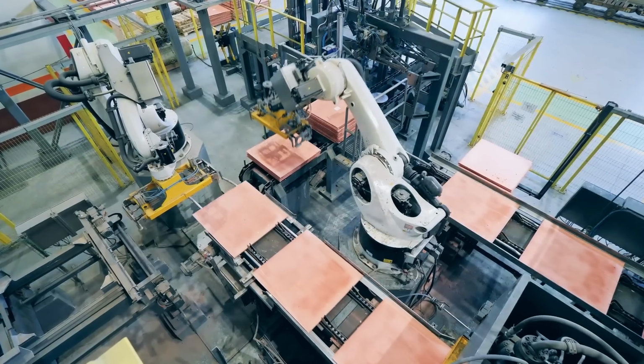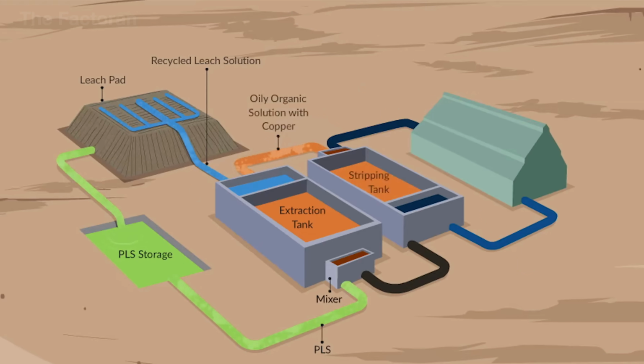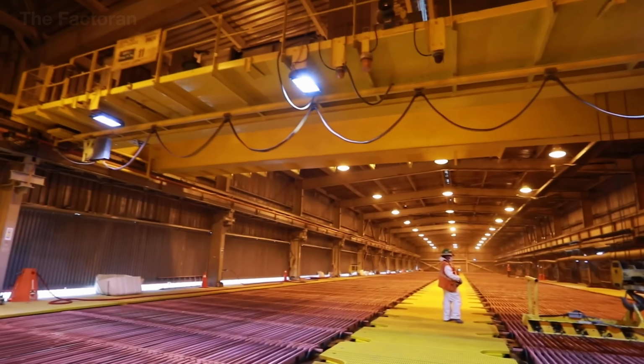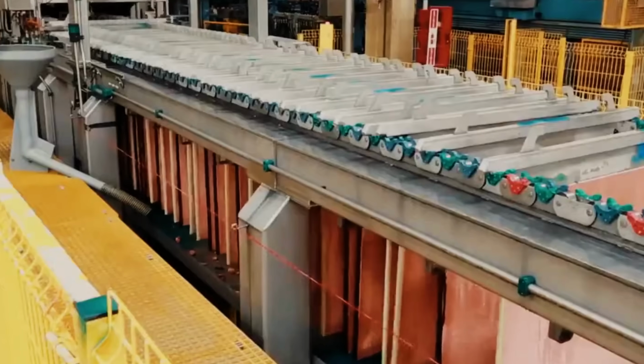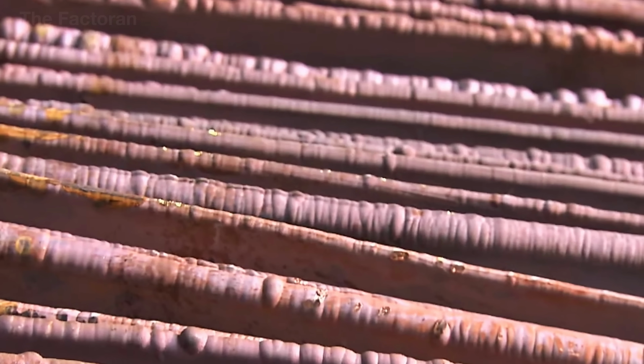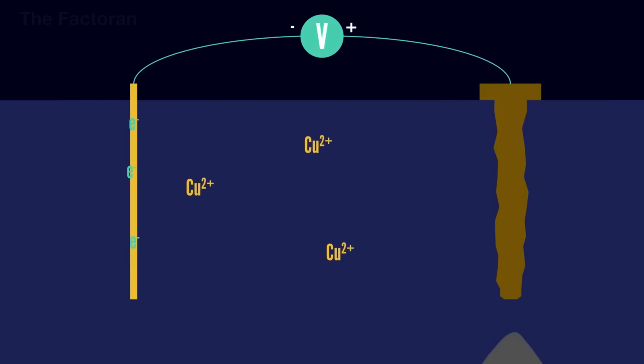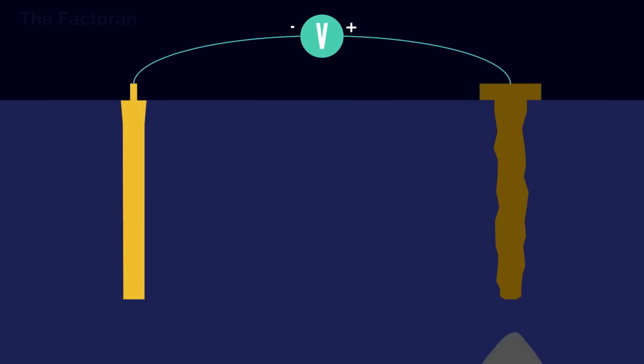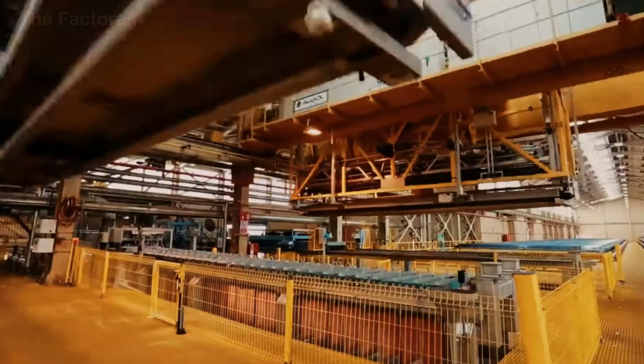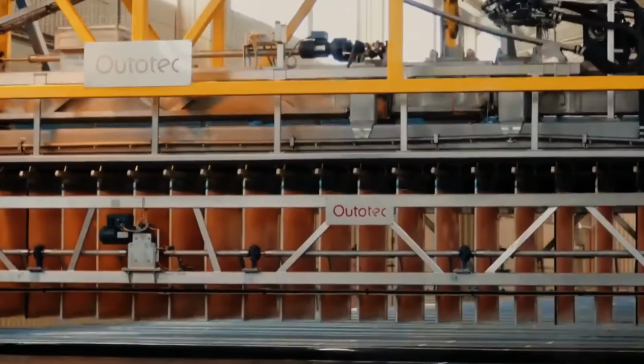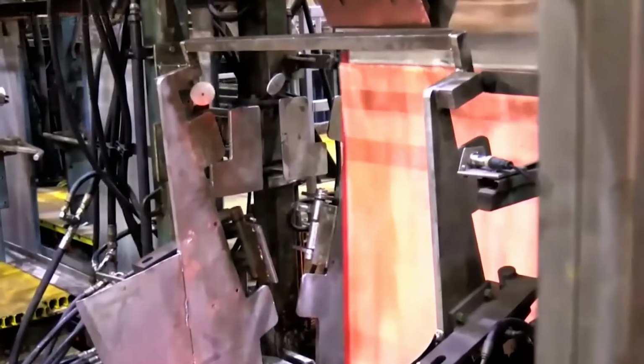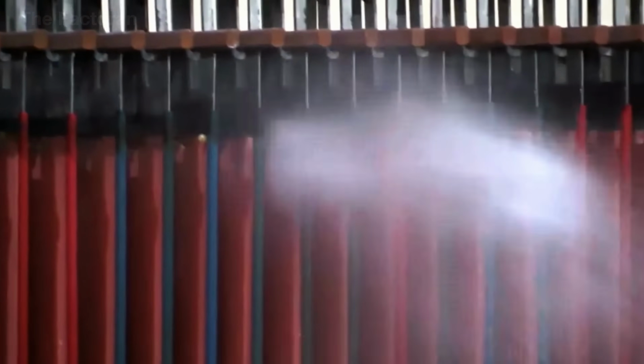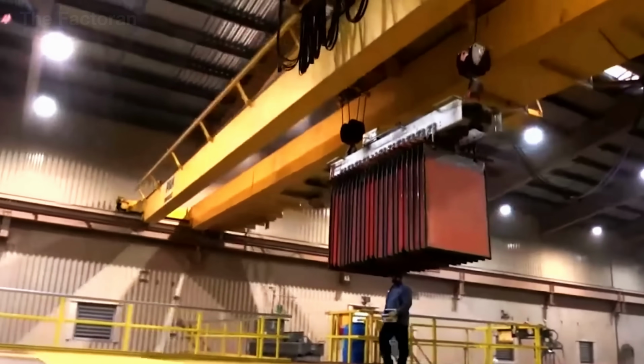After being reheated and cooled, the blister copper slabs move on to their final transformation, electrolytic refining. In massive tanks, filled with a solution of copper sulfate and sulfuric acid, the crude copper anodes are suspended alternately with stainless steel cathode plates. When a direct current is applied, copper from the anodes dissolves into the solution, then migrates and recrystallizes onto the surface of the cathodes, forming a layer of copper that is almost perfectly pure. This process takes between 7 and 10 days.